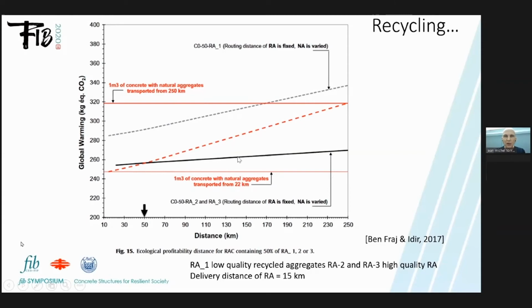Sorry. And you see, of course, that there is a big influence of the distance, and that if the natural aggregates are coming from more than 50 kilometers, it's better to use recycled aggregates in this case. So the conclusion, of course, is in the case of good quality aggregate. So there are two conclusions. The first one is, of course, very important, the sorting of recycled aggregates. You have to eliminate all the other materials from your concrete recycled aggregates. And in this case, it's better.